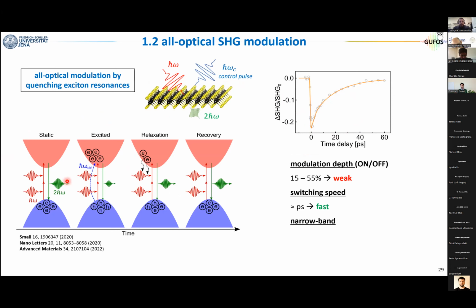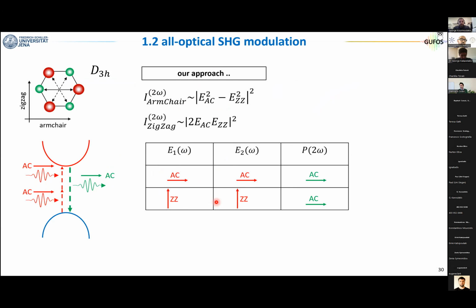And the idea is that the second harmonic must be resonant with the band-to-band transition, so with the exciton of TMDs. The control pulse generates electron holes in the valence and conduction bands. And as you generate these new electron holes, you reduce, let's say, the strength of your optical transitions, and the second harmonic will be quenched. So now the advantage is that the speed is much higher. The disadvantage is that the modulation depth is lower, but there is another big disadvantage, that this method is now very narrowband. So this method only works if your fundamental beam or your second harmonic is at resonance with the exciton. Otherwise, you cannot have any quenching. And this is where we came with our idea, where we thought, okay, is there a way of combining the best of the 2 approaches? So very large modulation depth and very high speed with an ultra-broadband bandwidth.